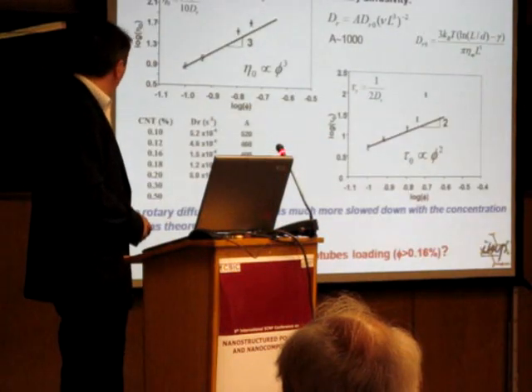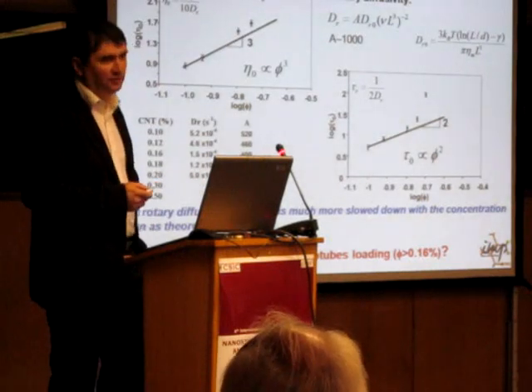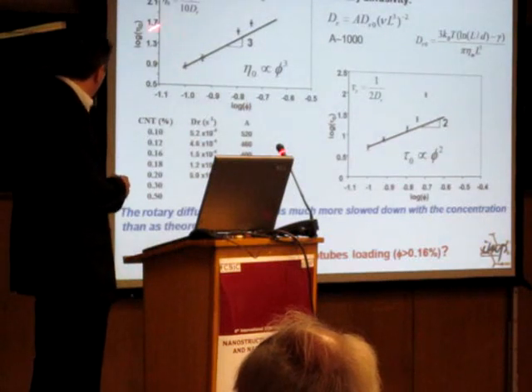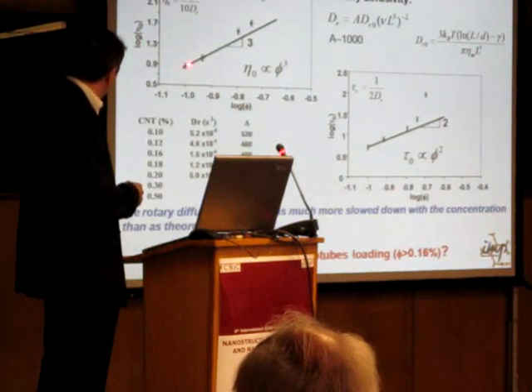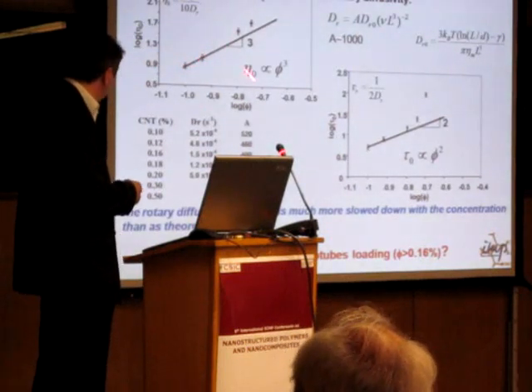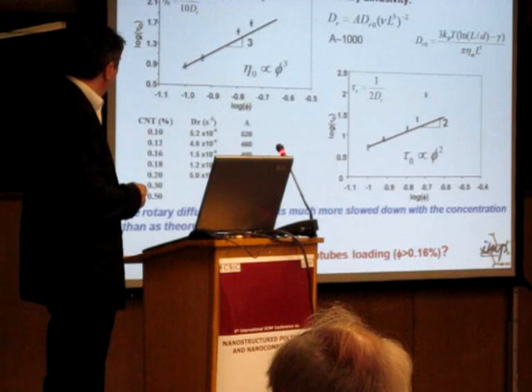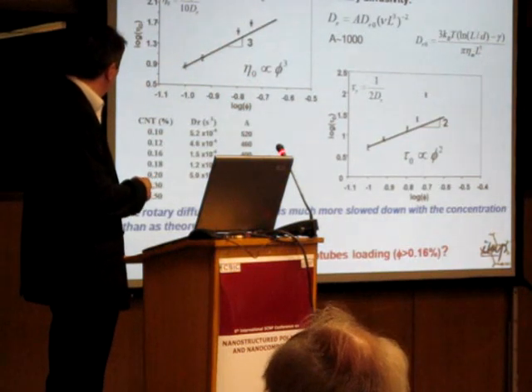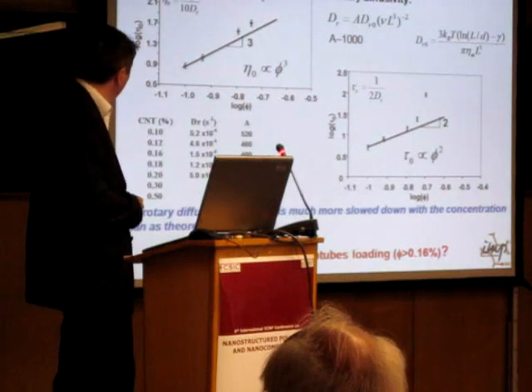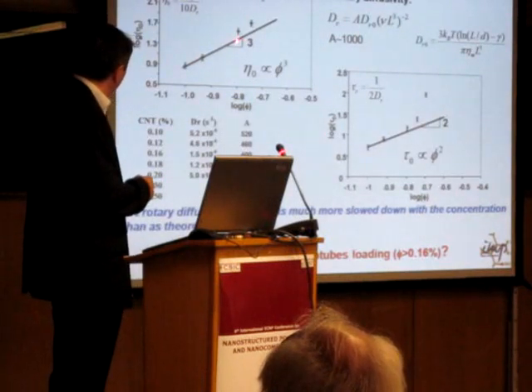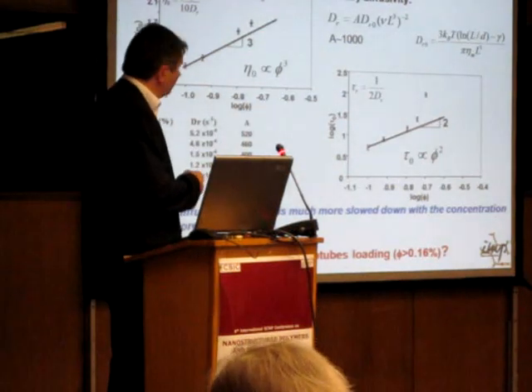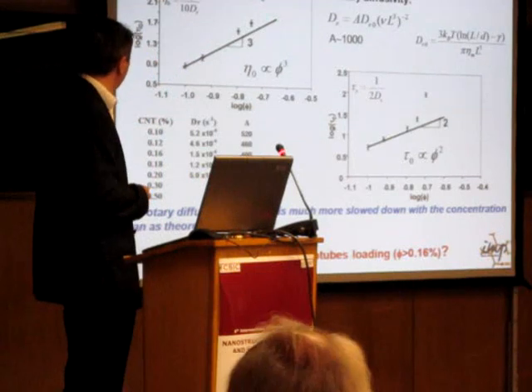What about the variation of the zero shear viscosity and the relaxation time? You observe that the viscosity, the zero shear viscosity increases obviously with the concentration. And here is the prediction of the Doi-Edwards theory with the slope of three. And you can observe that above 0.15, a strong deviation from the theory.